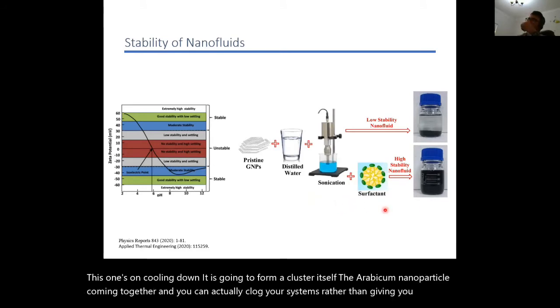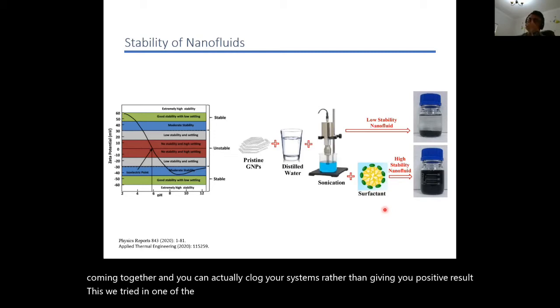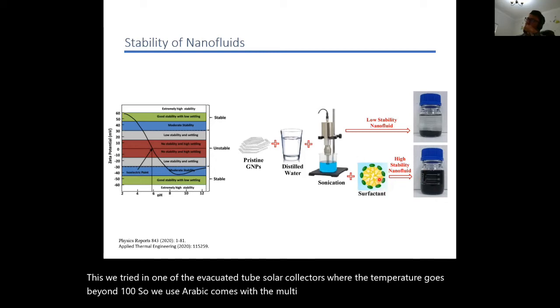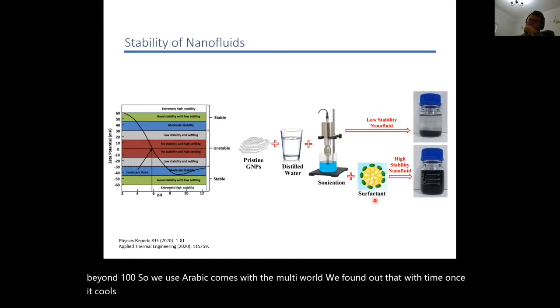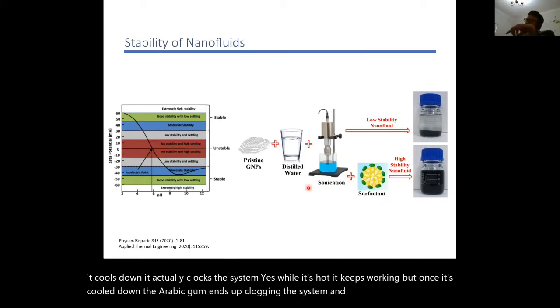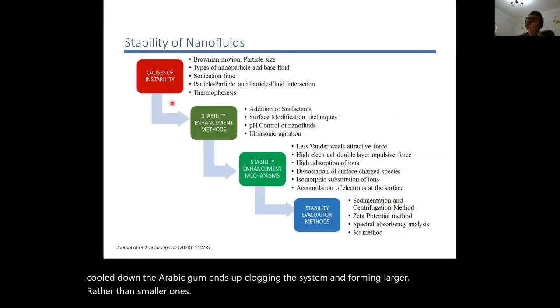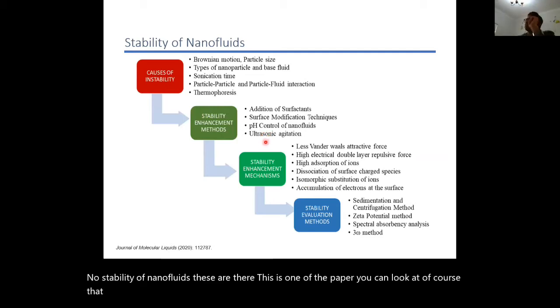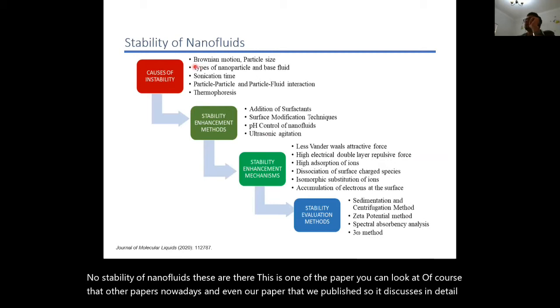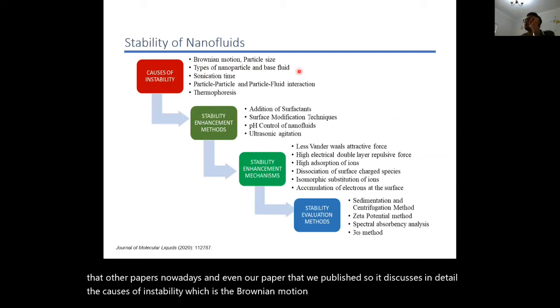We tried this in one of the evacuated tube solar collectors where the temperature goes beyond 100. We used Arabic gum with the multi-wall nanotubes. We found that with time, once it cools down, it actually clogs the system. While it's hot, it keeps working, but once it's cooled down, the Arabic gum ends up clogging the system and forming larger particles rather than smaller ones. Now, stability of nanofluids. This is one of the papers you can look at. Of course, there are other papers nowadays, and even our paper that we published. It discusses in detail the causes of instability, which are Brownian motion, particle size, type of nanoparticle and base fluid.